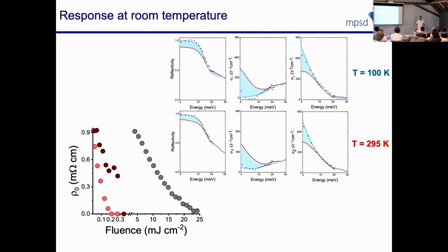The gap frequency is about 12 meV, with the caveat that, as you well know, potassium C60 has a large polaron here. So it's not clear whether we're seeing the gap. Because remember, if you look at George's data, what you see is that the gap is not closing. It's being filled in from below. The gap stays fixed, but it's never clear whether this is a gap or a polaronic feature. Anyway, 12 meV as opposed to 4. Yeah, larger than the equilibrium gap, let's say.